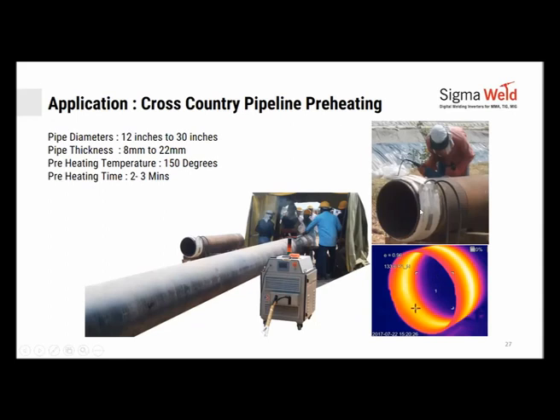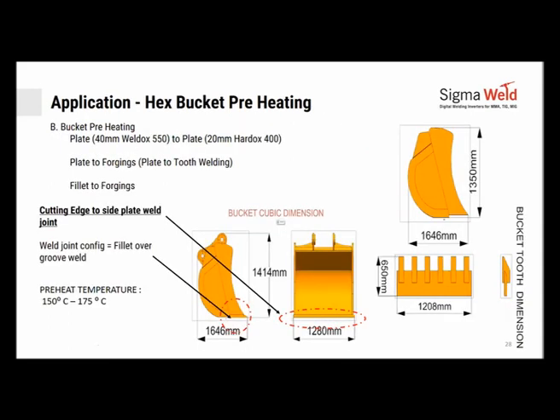The other way around from this is using gas to preheat the surfaces, not usually able to get equal heat, and also the risk of overheating and ruining your coating on the other side. This has been successfully executed on many GAIL projects across India. More than 50 equipments of this nature are working in India and now also in the Middle East. Pretty much a standard application for pipeline preheating.